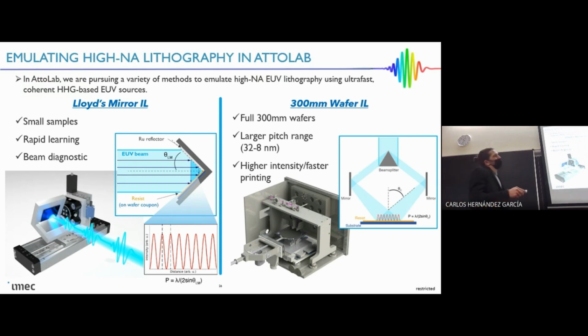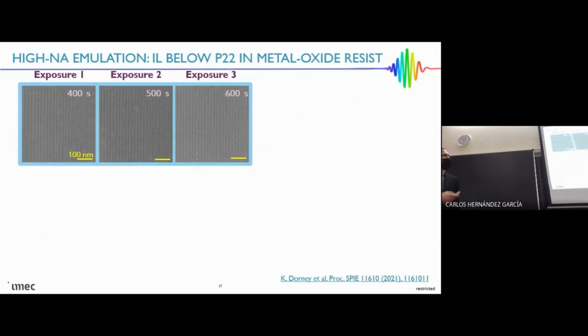I won't talk too much about this chamber, because it's still being built out. But for that Lloyd's mirror device, we were actually quite successful already in printing lithographic patterns with 13 nanometer light. Here it might be a little bit difficult to see, but you can see those linear grating patterns on an exposed coupon sample. This one is with a metal oxide resist that's a little different than the ones I mentioned previously.